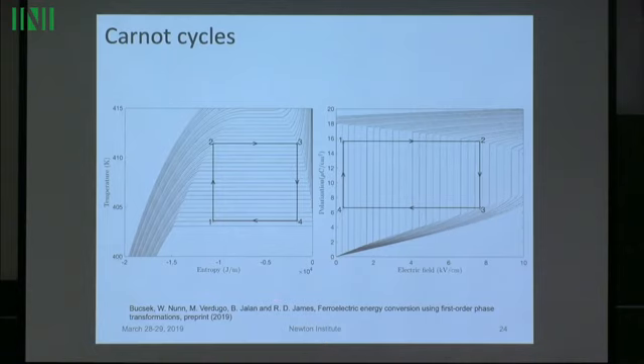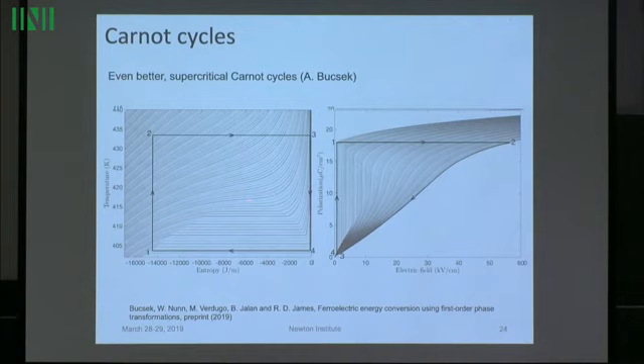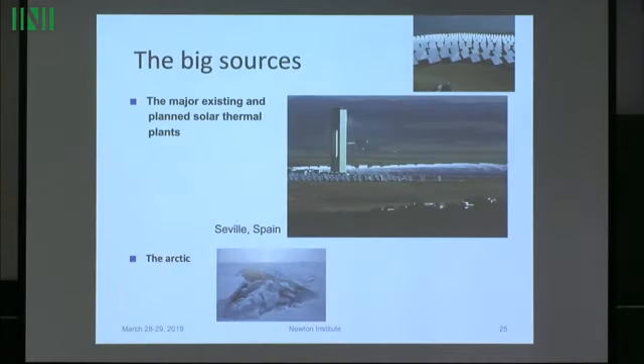There are some pictures of those that would be good from the point of view of the first lecture. But also, if you look at this model, it actually has a critical point here. So this is the mixed phase region. But above the critical point, these lines are not so steep. What this means in practice is that you can make much bigger cycles, have bigger temperature differences, so higher efficiencies, and these are not so bad cycles to use. And just as in steam generation, people also use supercritical cycles of this type. It does seem like an interesting thing to do, so we're doing that.